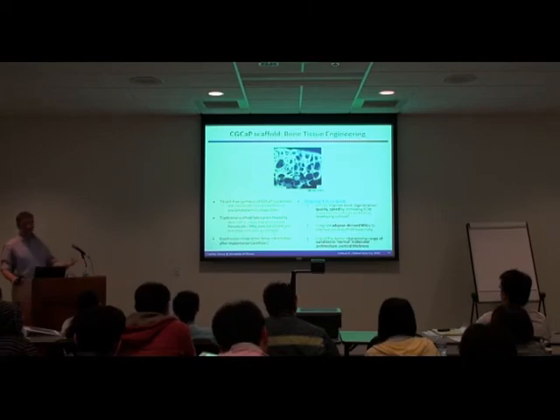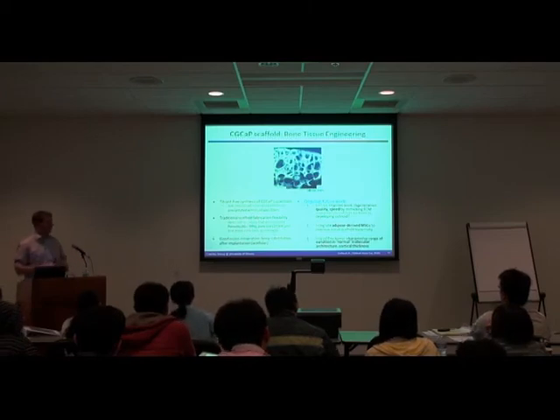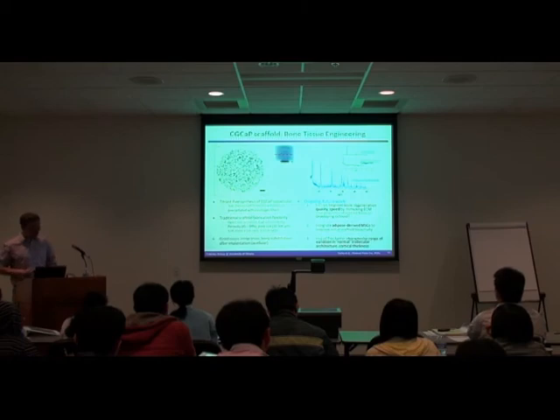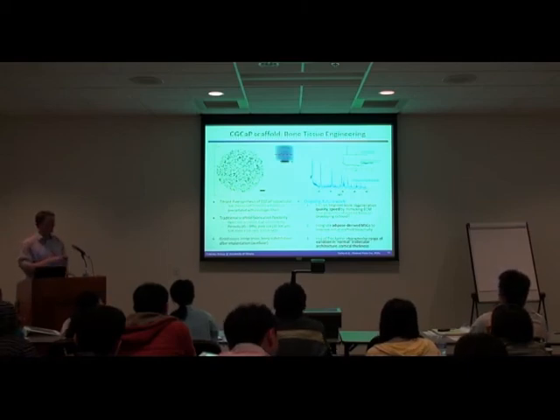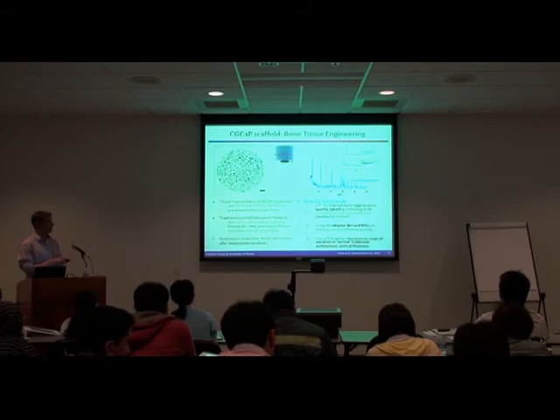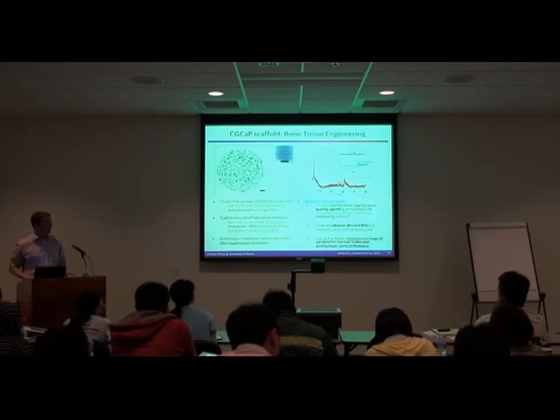Then you go through your freeze drying step to set the pore size and shape and all that sort of fun stuff. We've ended up coming up with this three-dimensional mineralized scaffold. It's got a relative density of about 15%, so it's about 85% porous. It's one of the more highly dense scaffolds you produce. And it's produced with a brushite phase of calcium phosphate, and we can use hydrolysis steps to change it from brushite to octacalcium phosphate to apatite, which are a lot of different features of a biomaterial that we might care about.